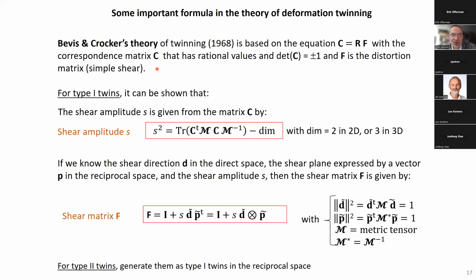What is important to me is that inside this theory, there is an important relationship that completely astonished me when I read the paper. It is here, is that you can calculate the shear amplitude of the twin without calculating the twin distortion. What we need is we just need to know what is the correspondence between the parent and the twin. And it is a rational, you remember, it is a rational matrix here. What we need in addition is the metric tensor.